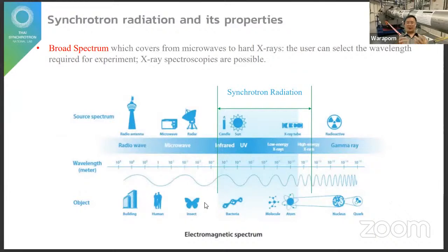And the synchrotron beam actually has a broad spectrum. It covers from infrared to X-ray. If you have a higher energy electron storage ring, you can go even to hard X-ray. Like in our machine, the maximum energy of X-ray we can get is about 30 keV, and the lowest is from the infrared beam line. And if you go to SPring-8, they can perform very hard X-ray experiments, like 80 keV or 100 keV experiments.